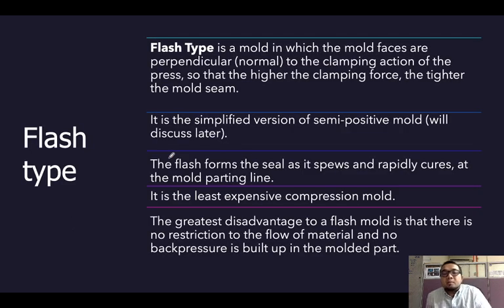So flash type is a mold in which the mold faces are perpendicular, normal to the clamping action of the press, so that the higher the clamping force, the tighter the mold seam. It is the simplified version of semi-positive mold. The flash forms the seal as it spews and rapidly cures at the mold parting line. It is the least expensive of the compression molds. The greatest disadvantage to a flash mold is that there is no restriction to the flow of material and no back pressure is built up in the molded part.